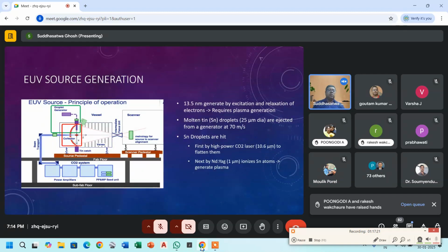What this bombarding does to the electrons is that the tin atoms are ionized and generate plasma. Once they relax back from the ionization state, they generate this 13.5 nanometer light, which is used as the source for these EUV scanners that I spoke of. The process is really complicated, quite interesting, and also quite challenging. Here we use CO2 lasers which generate 40 to 50 kilowatts of power. ASML invested a lot of time and energy, in conjunction with our partners, and it was almost a development period of 20 years until they came up with this machine, which can do projection lithography on EUV systems.